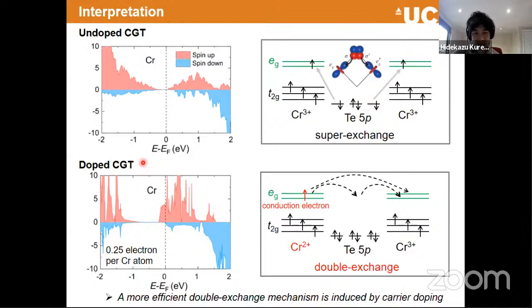Now, if you think about the doped case, the critical difference is that now we put real electrons in the EG band. By calculating from the carrier density, we can tell that 1/4 of this chromium 3+ states is doped by one electron and becomes chromium 2+ states. In this regime, an additional exchange mechanism can be promoted. In particular, this is almost delocalized, therefore it can hop around everywhere, either through tellurium ions or just direct coupling between different chromium ions. So that can clearly promote magnetic coupling between these two ions.